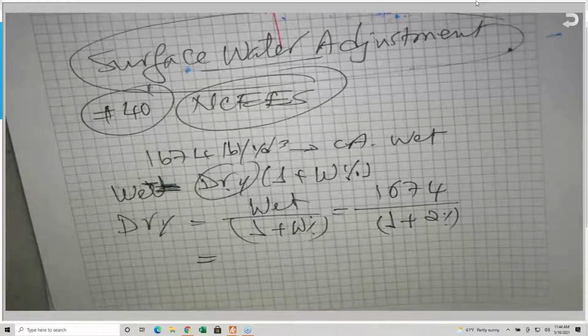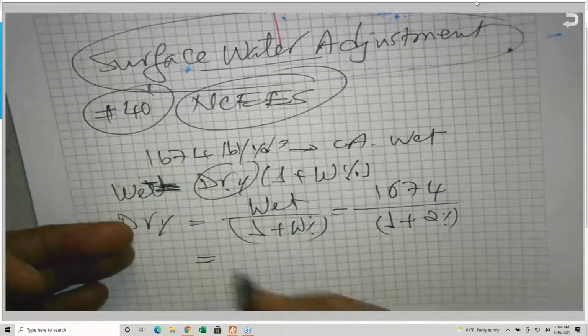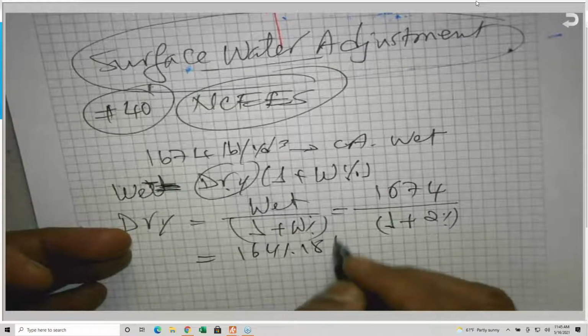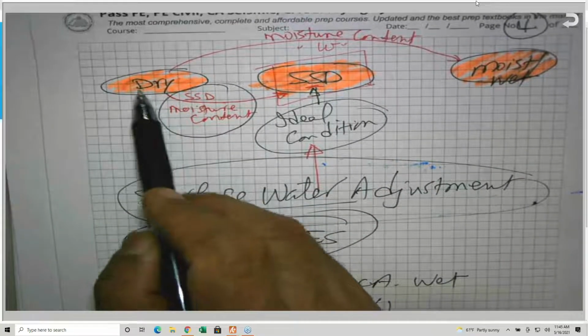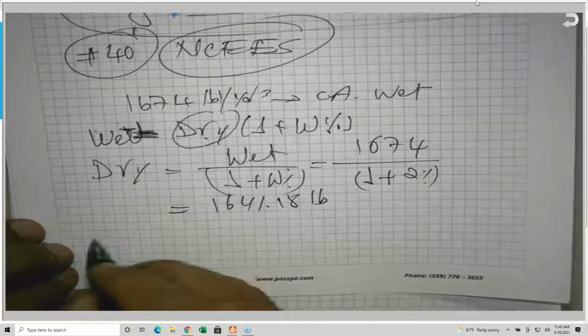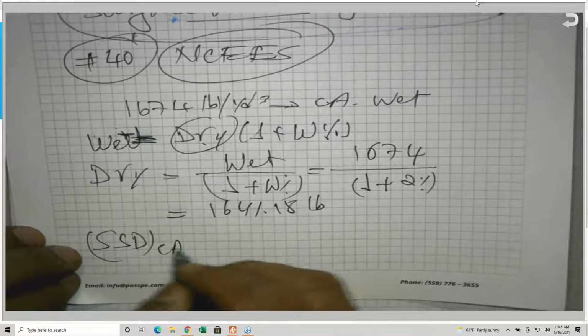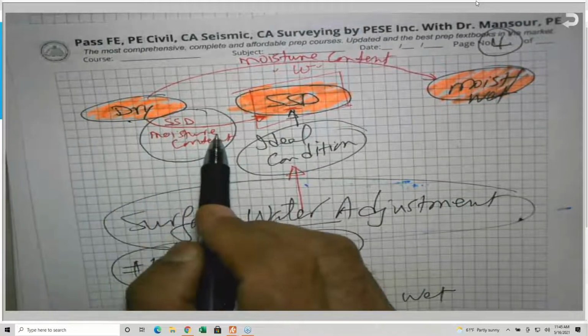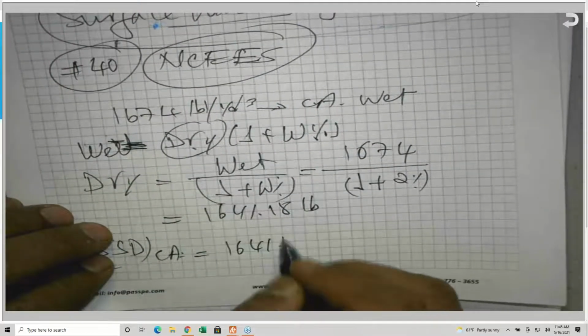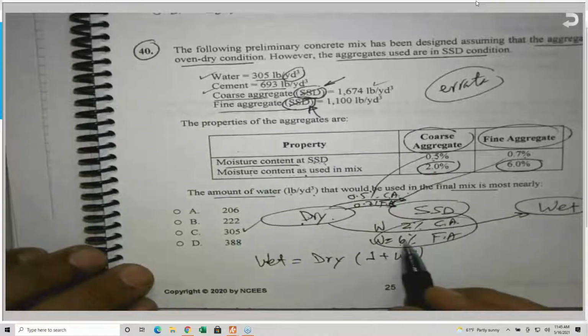Let me see here. 1.02. Okay, so 1674 divided by 1.02 equal. So this will give you 1641.18 pounds. So by doing this, I bring the coarse aggregate from the moist to the dry, but I need to bring it to the SSD. So I will say the SSD weight of the coarse aggregate. I will take the dry and multiply it by the 1 plus, so the dry, which is 1641.18 pounds, times 1 plus. How much do I need to reach SSD? Here it is. For the coarse aggregate it is just 0.5. So times 1 plus 0.5.